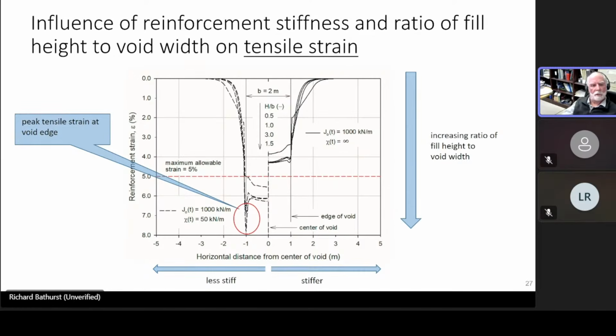And in this particular example, you can see that if one used the more creep-prone reinforcement, then you're going to have strains that exceed the maximum allowable strain of 5%. So this would disqualify these particular reinforcement products because they do not satisfy the strain limit state.